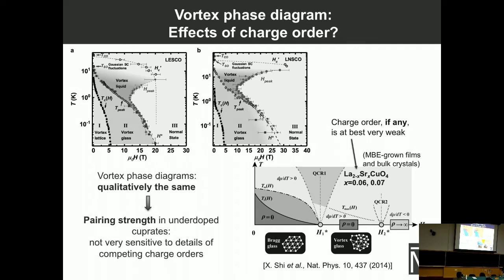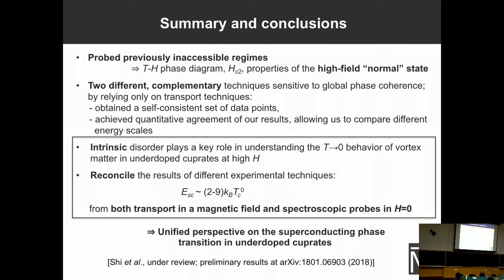So basically, this is the summary. We were able to explore previously inaccessible regimes, which allowed us not only to map out this vortex phase diagram, but also to probe this unusual high field normal state. By relying on transport techniques, we have been able to obtain quantitative agreements between our results. And so the key result found here is, I think, that the intrinsic disorder plays a key role in understanding the behavior of the vortex matter in the zero temperature limit.